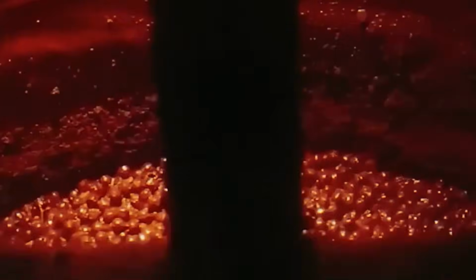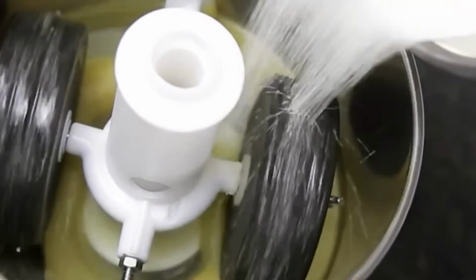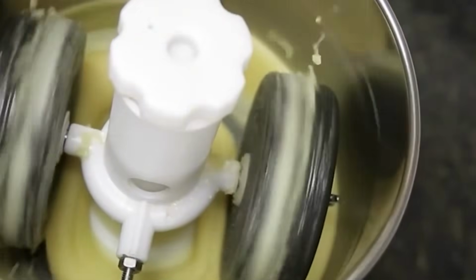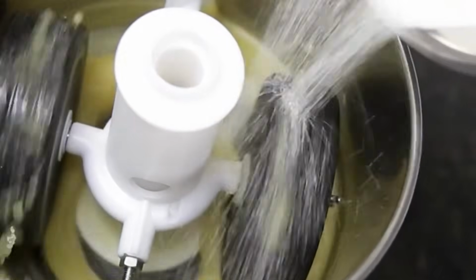This liquor is heated slightly to reduce viscosity and then transferred to high-pressure hydraulic presses that squeeze out the cocoa butter, leaving behind a dense cake of compressed solids which are ground into cocoa powder. For milk chocolate production, the cocoa liquor is blended with refined sugar, high-quality milk powder, additional cocoa butter, and in some recipes, a hint of vanilla or lecithin, which acts as an emulsifier.